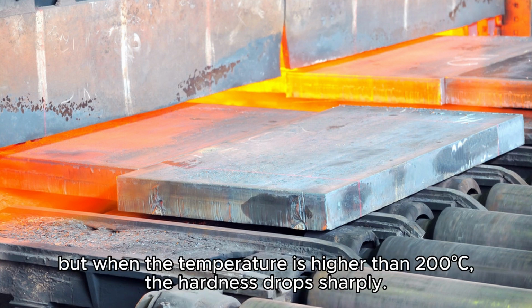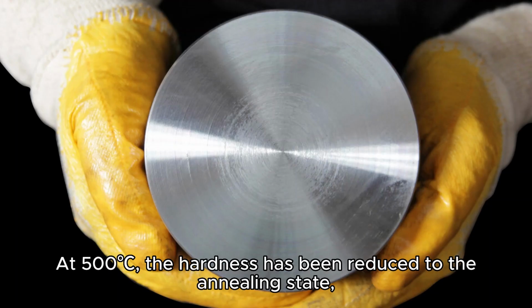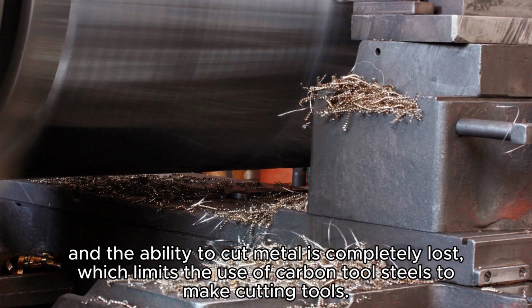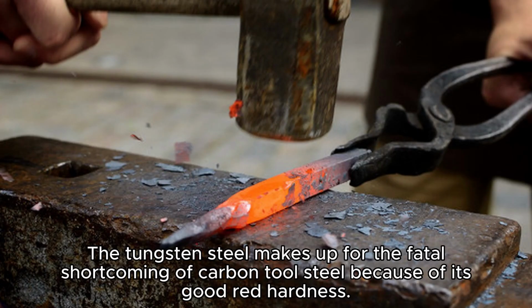But when the temperature is higher than 200 degrees centigrade, the hardness drops sharply. At 500 degrees centigrade, the hardness has been reduced to the annealed state, and the ability to cut metal is completely lost, which limits the use of carbon tool steels to make cutting tools. Tungsten steel makes up for this fatal shortcoming of carbon tool steel because of its good red hardness.